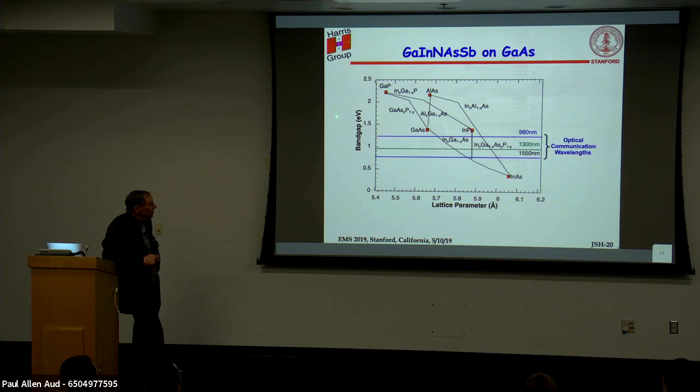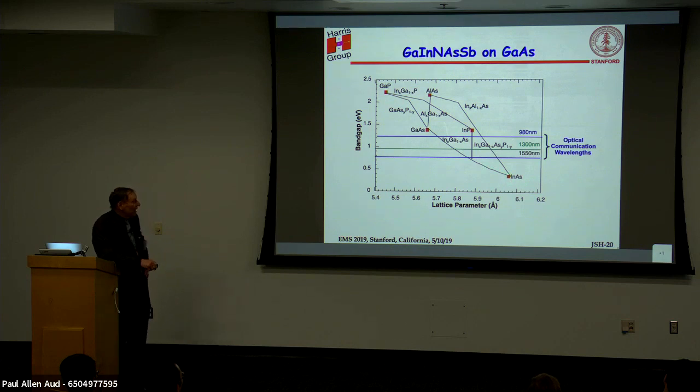So if you look, this is the family of materials that those of us that have worked on the 3-5 materials for the last 50 or 60 years knew well, that, to first order, as you increase the lattice constant, the coupling between the atomic levels was reduced, and so the band splitting and the band gap were lower. And so you can see this general trend, and it just turned out you can't see anything that lattice matches to gallium arsenide out here.